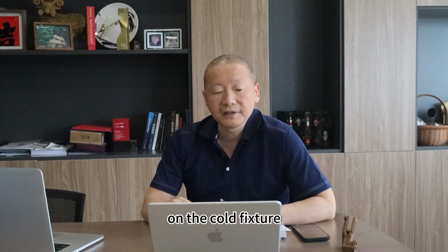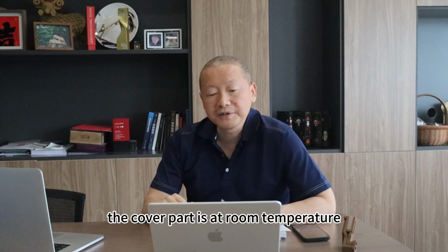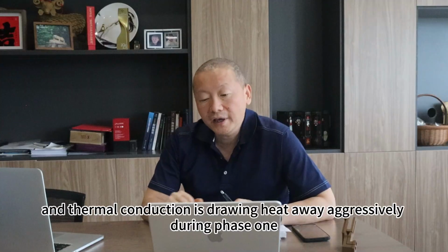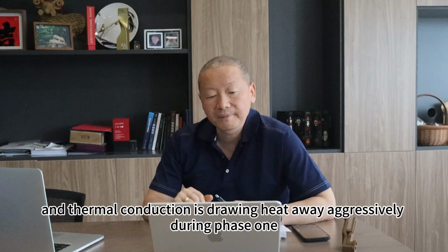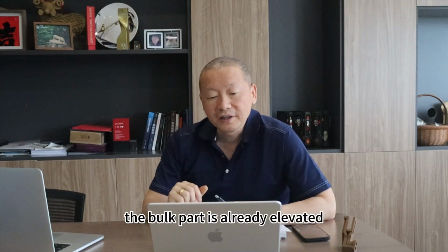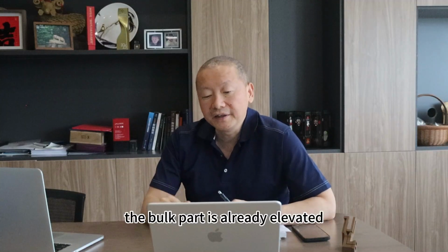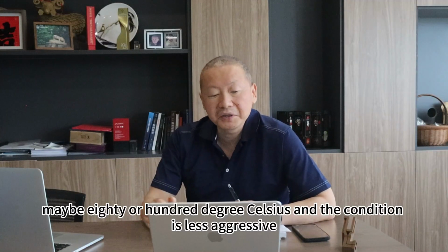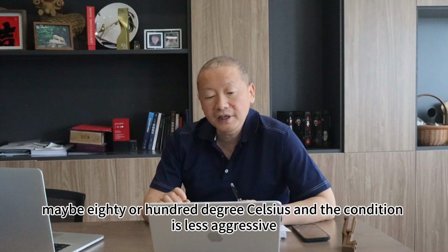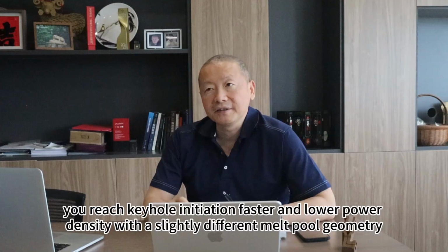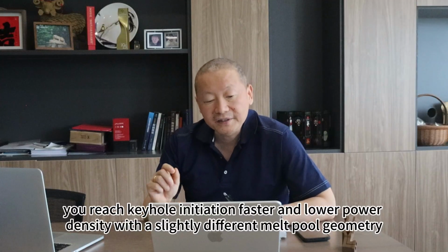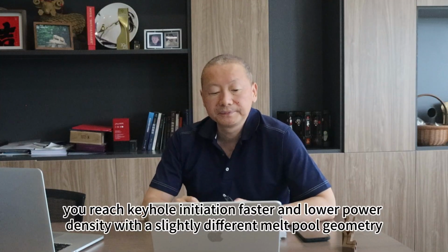On the cold fixture, the copper part is at room temperature, and the thermal conduction is drawing heat away aggressively during phase 1. On the warm fixture, the bulk part is already elevated, maybe 80 or 100 degrees Celsius, and the condition is less aggressive. You reach keyhole initiation faster at lower power density with a slightly different melt pool geometry.